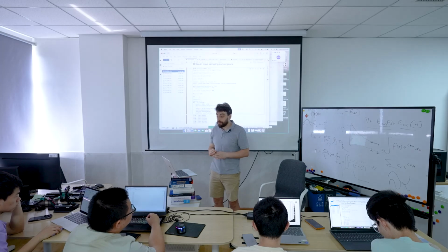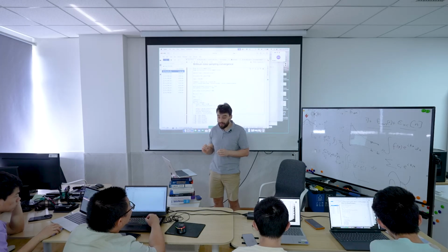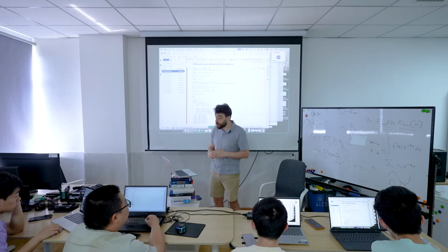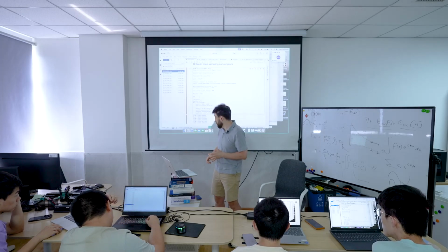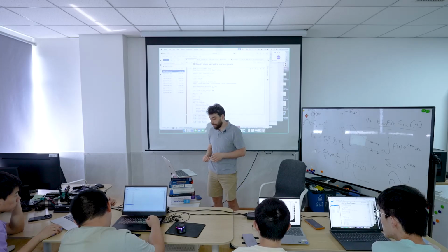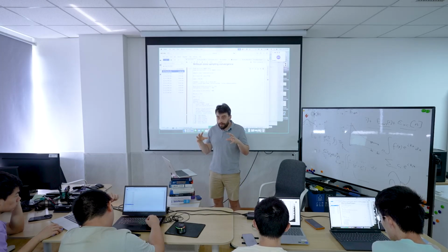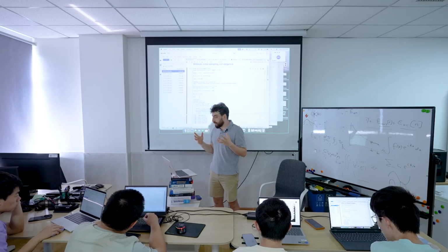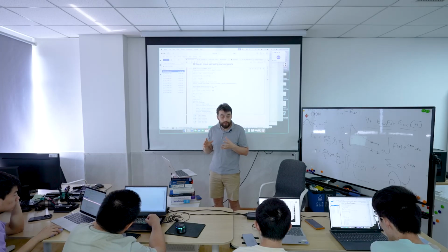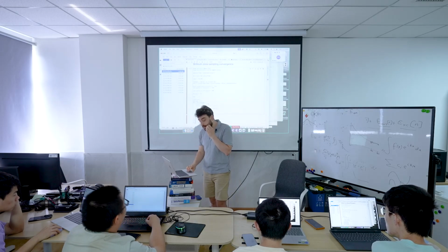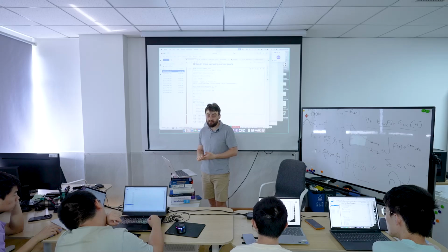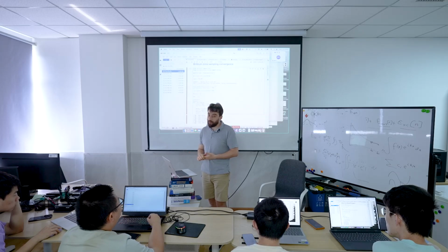In some systems, you do not get convergence until you get 30 by 30 by 30 k-points, which is a huge calculation. An example of that is arsenic, or As, on the periodic table. It has a very quickly varying Brillouin zone, so it needs very tight sampling. But most metals are somewhere between 4 by 4 by 4 and maybe 12 by 12 by 12, depending on the metal.